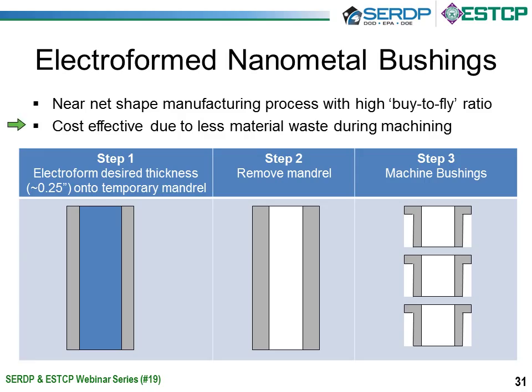So an example of the process, the first step would be you coat the material onto a mandrel of about the diameter of the bushings that you want to make. And a typical wall thickness in the bushing is about 1/4 of an inch. The second step would be then you remove the mandrel, so you result in just basically a shell of material or a cylinder, which then can be machined into bushings.